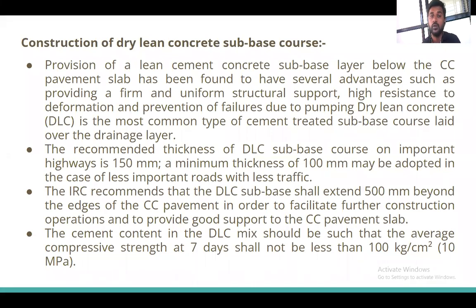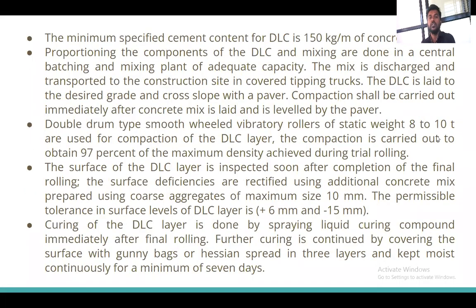Whatever cement we are using in the DLC, it should give an average compressive strength at 7 days of 100 kg per centimeter square. That we have to check. Also, the cement content should be a minimum of 150 kg per meter cube of the concrete.